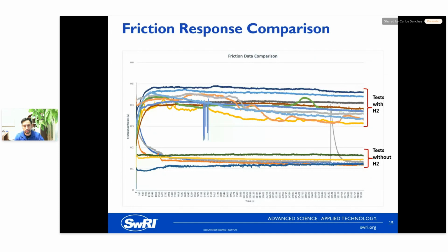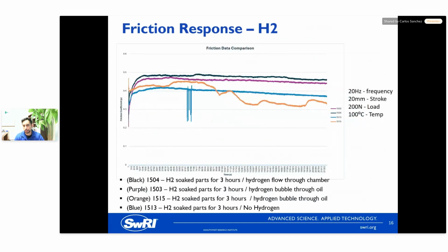Getting to look a little more closely, here's a breakdown of a couple different methods we used to introduce hydrogen. So H2 soaked for 3 hours and hydrogen flow throughout the chamber. That's the upper graph there, that black curve. So you can see that that's probably the worst case scenario as far as introducing hydrogen. So you can see that the friction coefficient is a lot higher there. The next graph down, again, soaked in hydrogen and bubbled through the oil. So again, it's fairly similar. So the main part is just having it soaked for 3 hours for your parts and have a continuous flow of hydrogen throughout your system, either through the oil or in the environment.